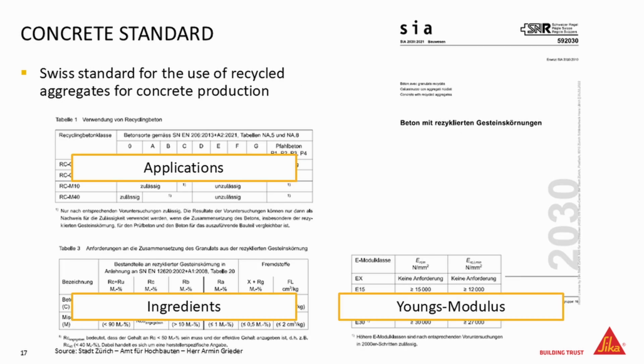So this started already in about 2000, that you first need to have standards for this. Concrete production is highly regulated, and if you want to change now from natural aggregates to recycled aggregates, you need to have a standard for this. You need somehow to implement a QC of that, and that is why in Switzerland there is this regulation for recycling concrete and also for recycling aggregates. So basically what is in there is regulated applications for concrete using recycled aggregates.